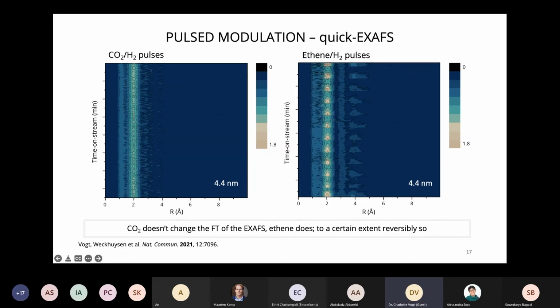So here we see about 70,000 of those spectra plotted with time on stream, going from 0 to an hour about, and we pulsed back and forth ethene and hydrogen, ethene and hydrogen, and CO2 and hydrogen, etc. Here we see no real significant changes for our CO2 catalyst again, but we do see ordering and disordering, actually reversibly so, for the ethene pulsed experiment.